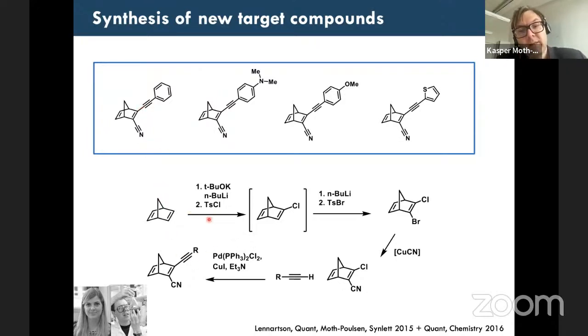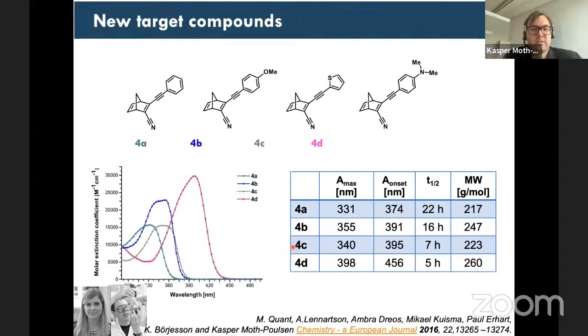And in this example, we have refined the way of making this bromochloro norbornadiene using non-toxic chemicals, so it becomes more scalable. And we have also used this stepwise reaction sequence where we have the Sonogashira reaction here in the end. So this was a few years back, but the result of this work was that we had molecules with very good optical properties. You see here the absorption spectra of these 4 molecules.